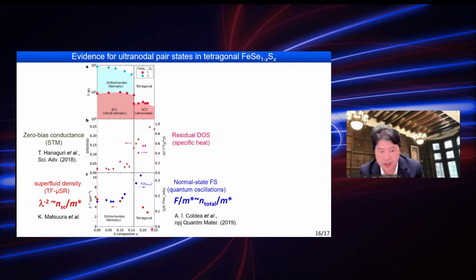As you can see, in the normal state, the Fermi surface is expanding if you increase the sulfur composition. However, the superfluid density, in the superconducting state, shows a decrease in the tetragonal phase.